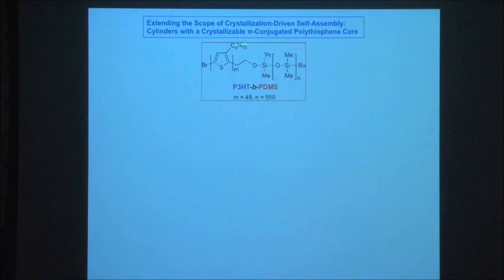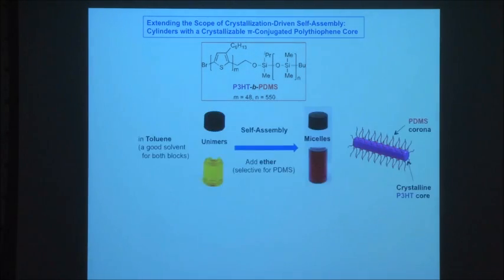Of particular interest, at least from our standpoint, is looking at pi-conjugated polymers like polythiophene, which will crystallize. So you can make poly-3-hexylthiophene-block-PDMS. Poly-3-hexylthiophene is a crystallizable block, so if you put this in a solvent that's good for the PDMS, you should get micelles where the P3HT will crystallize. First, you dissolve this in a solvent that's good for both blocks. So you put this into toluene. It gives you unimers. Toluene is good for both blocks.